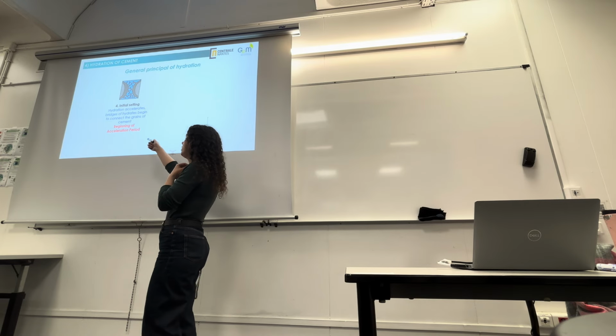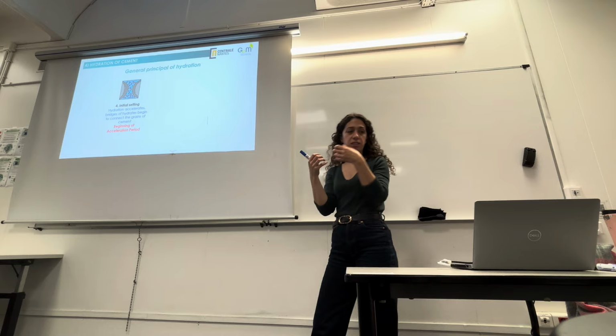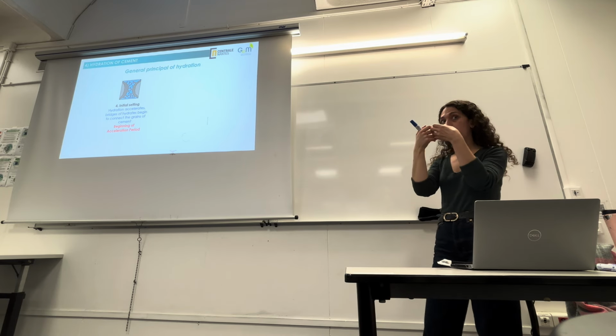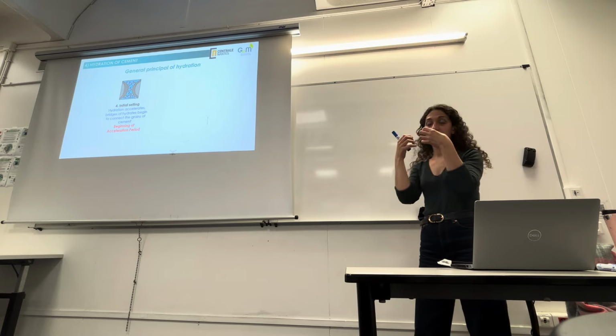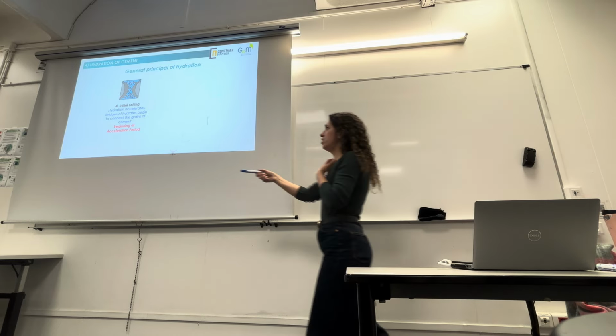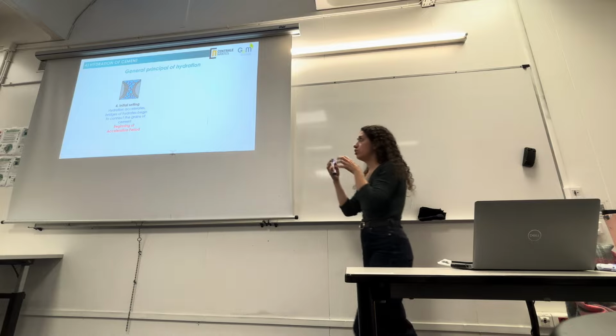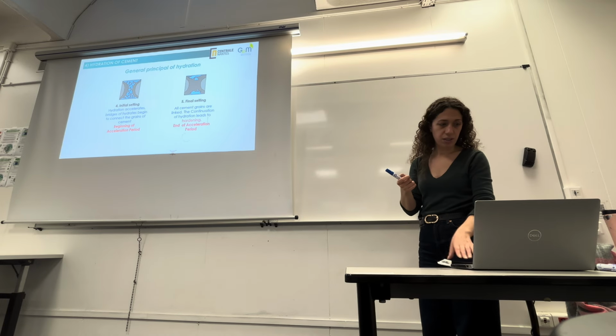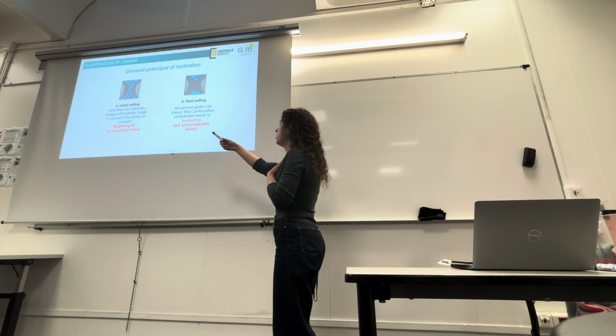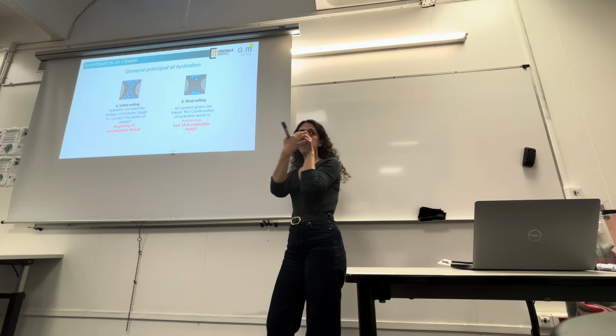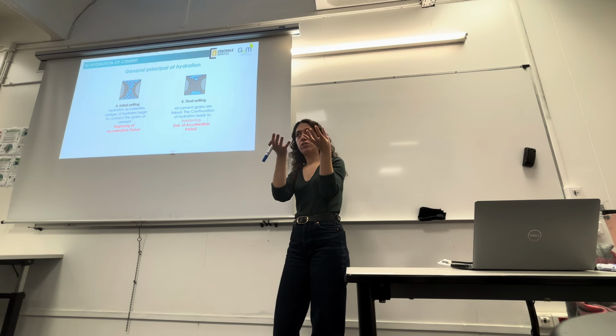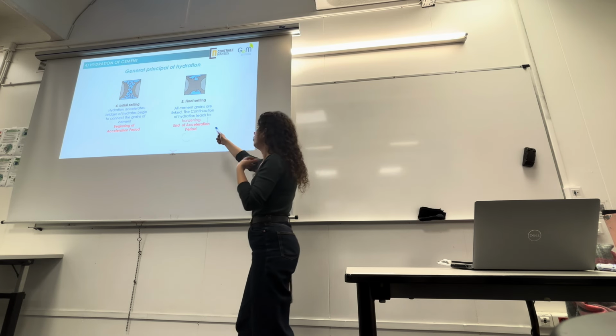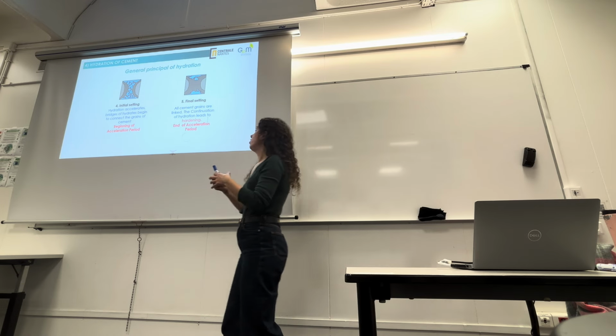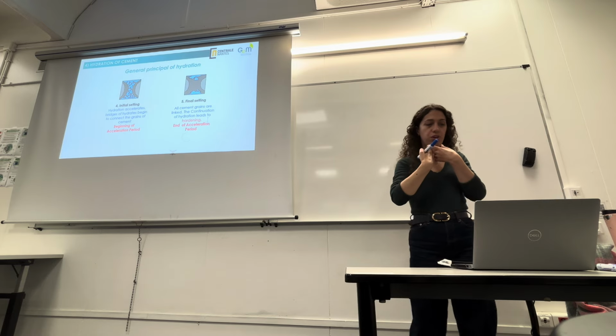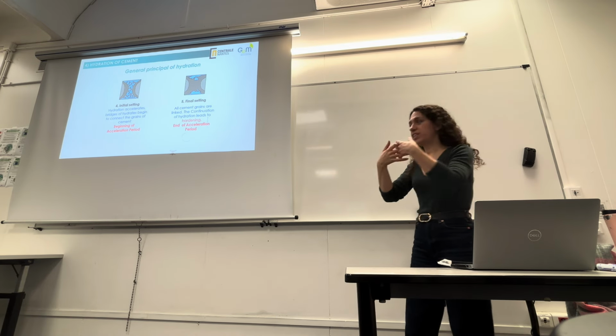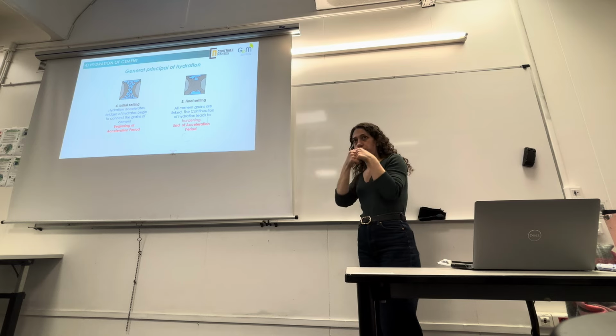Then you have initial setting. The hydration accelerates and creates bridges of hydrates between the grains. So now your cement is beginning its setting. This is the beginning of the acceleration period, the connection of the grains of cement by the hydrates. And during the final setting, all cement grains are connected and linked by the hydrates that have precipitated at the surface of the cement grains. So the continuation of hydration leads to hardening and the end of the acceleration period. Now the grains are all connected, and the connection only grows stronger. Okay.